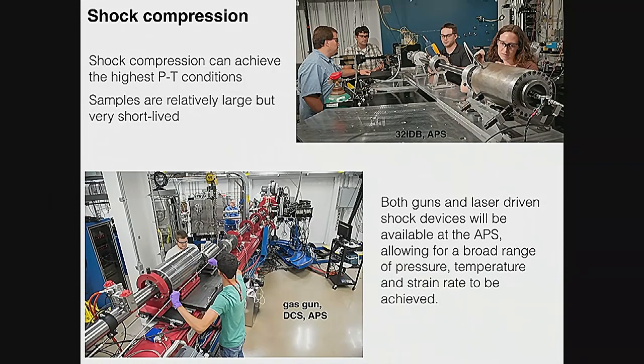Shock compression devices are usually basically guns, which are gas guns or powder guns, where you're shooting projectiles on a sample, or laser ablation ones. These are pictures from the APS. There are some, of course, around the world. By the way, I'm showing mostly APS US devices, but of course there's a larger worldwide high pressure community. And those at these laboratories are not the largest in the world. I showed you a picture from NNSA facilities. But they can reach extremely high pressure, but the sample, of course, has a very short life.